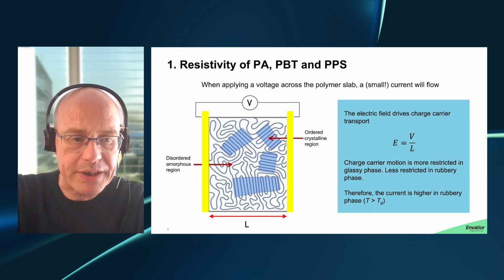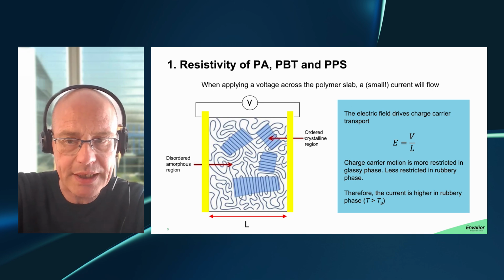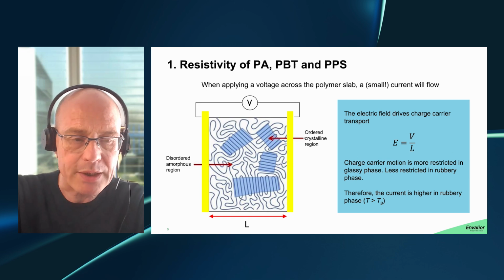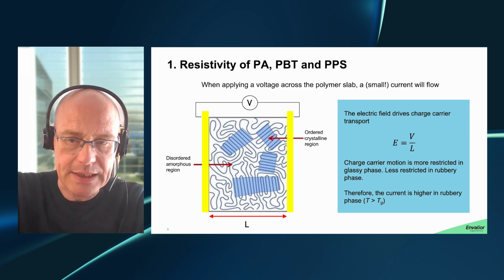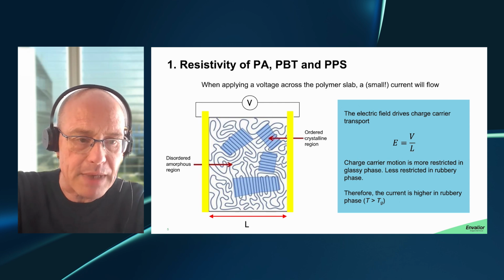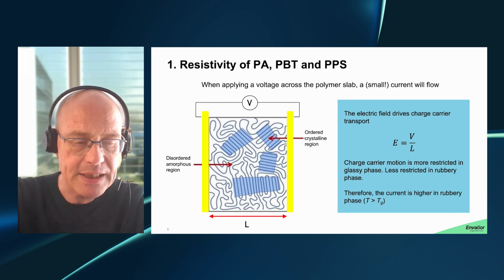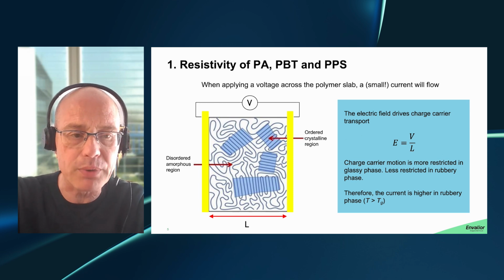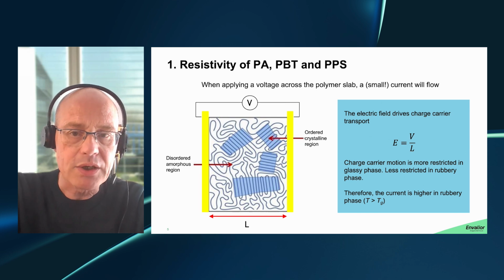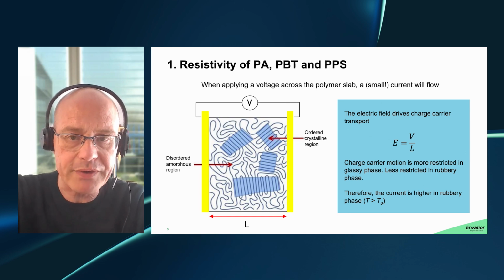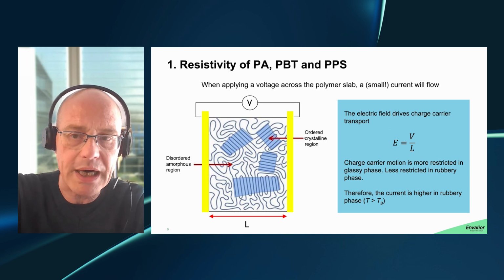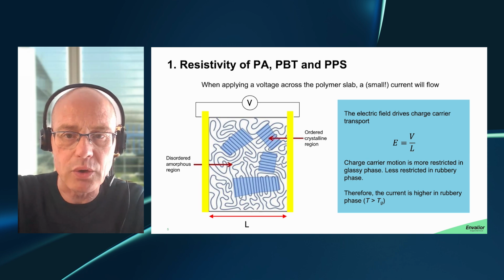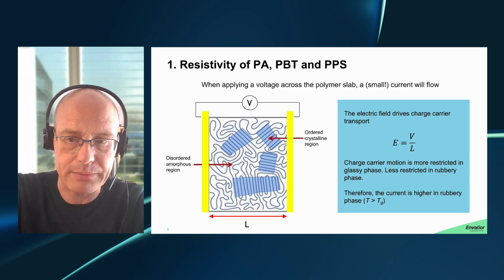If you take a polymeric slab and you put electrodes to it, here that is done with these yellow bars, and you apply a voltage across these electrodes, there will be an electric field that couples to the charge carriers in the amorphous phase of your polymer. And you can imagine that if the polymer is glassy, these charge carriers can move through the polymer much less easily than when the polymer is in the rubbery state. So clearly, the conductivity or the currents will be higher in the rubbery state and lower in the glassy state at lower temperatures.